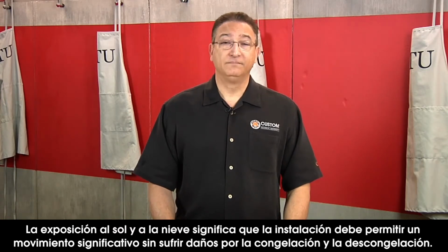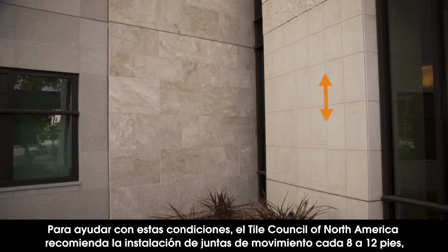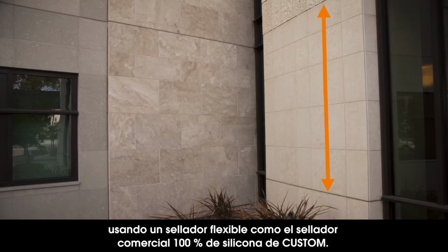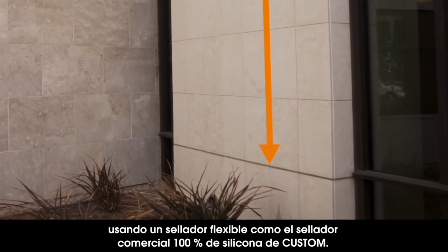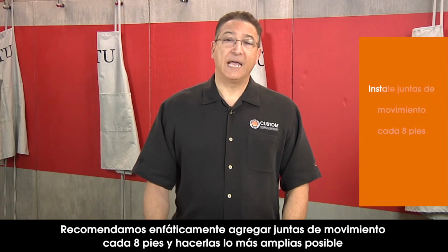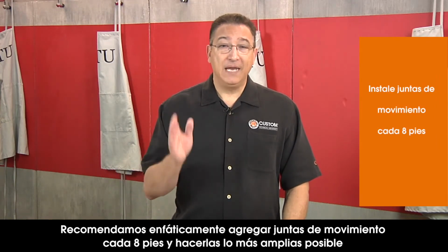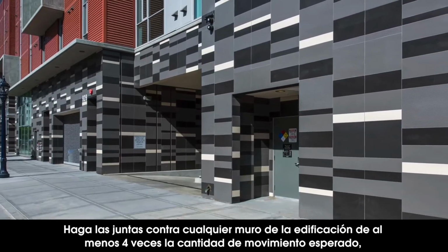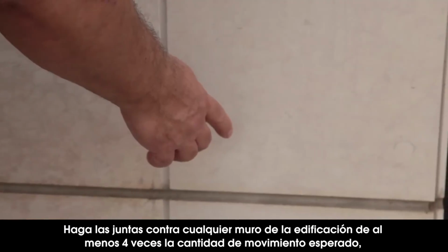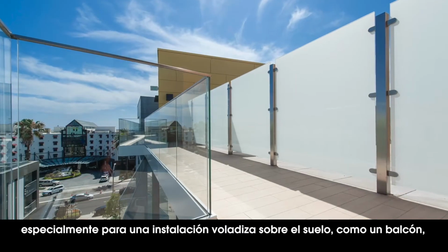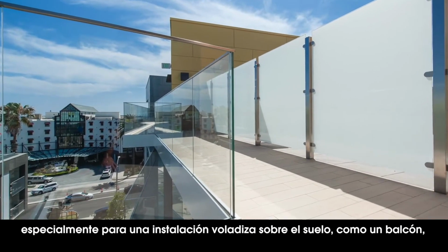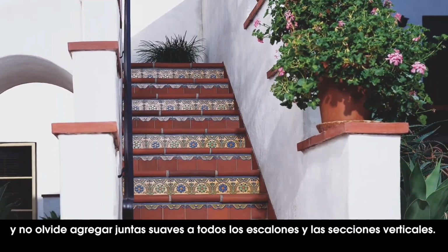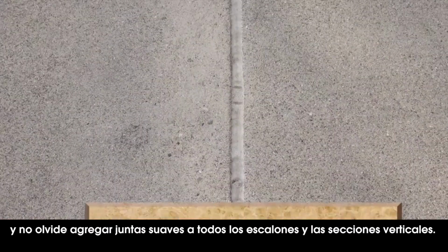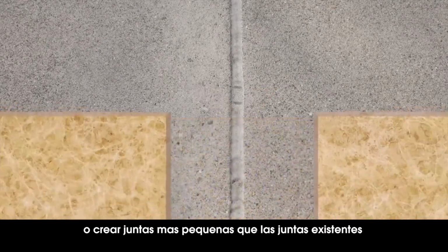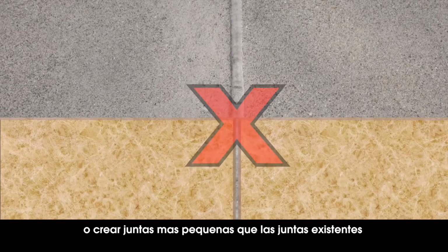To help with these conditions, the Tile Council of North America recommends the installation of movement joints every 8 to 12 feet and using a flexible sealant like Custom's commercial 100% silicone caulk. We strongly suggest adding movement joints at least every 8 feet and making them as wide as possible. Against any building walls, make sure your joints are at least 4 times the amount of normal movement expected, especially for an above-ground installation that's cantilevered like a balcony. Don't forget to add soft joints to all steps and risers, and never tile over joints in existing concrete or make the movement joints smaller than the existing joint.